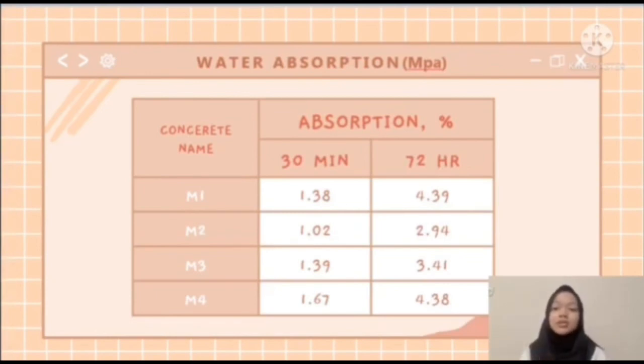These specimens were then totally submerged in water and their weight gain was monitored until they reached a stable weight. The concrete quality was assessed using absorption at 30 minutes and final absorption, which is when the difference between two consecutive weights is almost minimal. All of the concrete's final absorption was found after 72 hours. That's the final time for the water absorption test.